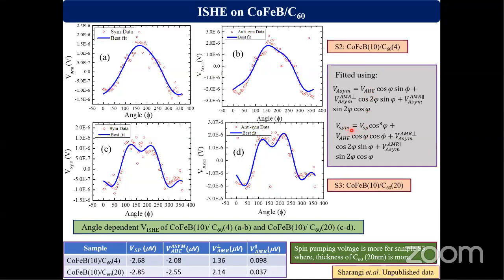Okay, sir. So this V symmetric part has contribution in the spin pumping and the anomalous Hall effect, and the V asymmetric part has contribution in the anisotropic magnetoresistance. So to calculate the spin pumping voltage, we have measured the angle dependent FMR and angle dependent ISHE measurement.